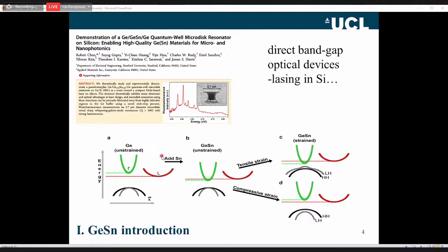However, if we add a very small amount of tin, the gamma level comes down and the L both come down, but the gamma level comes down faster with composition. The material switches over to a direct band gap. That's why we can see this photoluminescence. Very interesting photoluminescence. The spectrum here is rather complicated because there are all kinds of modes. It's not just a simple issue.